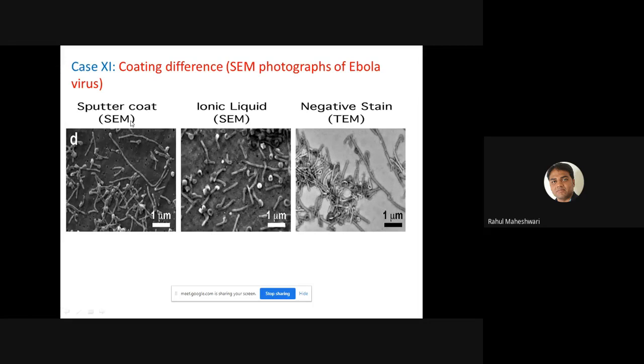This is the coating effect and nothing to do with the sample. This is just the coating effect. These fine ultrastructural details are not required during the sampling. And if you look at this ionic coating technique of the same, these ultrastructural details are reduced very significantly. If you compare this structure with this structure, then these ultrastructural details are not found here, right?